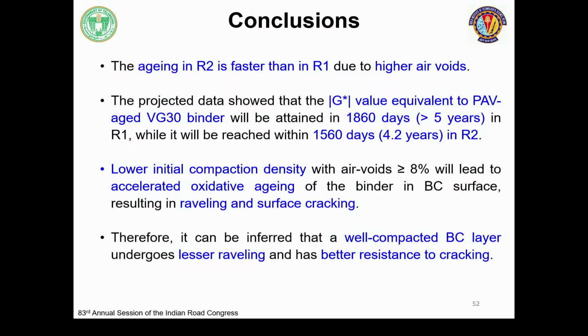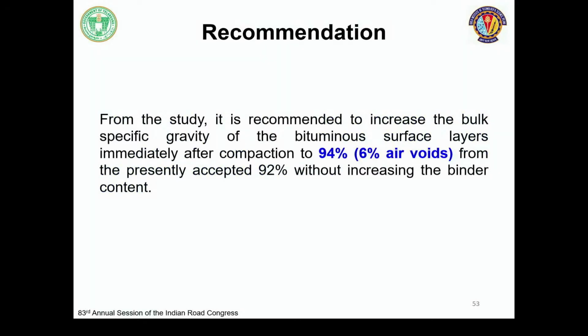I think now they are using 2% lime in the whole of Telangana and the roads are lasting more than 5 years. Therefore, it can be inferred that well-compacted BC undergoes lesser raveling and better resistance to cracking. One recommendation we would like to make in this study, based on the data which was collected every month, not biannually or so, is that if the compaction is done to 94%, because today's equipment is good and can compact to the extent we wanted, 94% with 6% air voids, we can increase the life of the pavement without increasing the binder content.